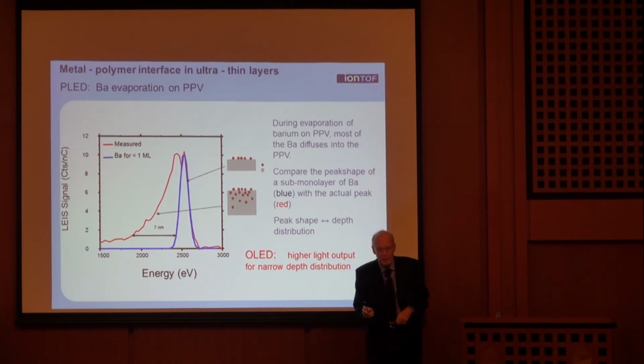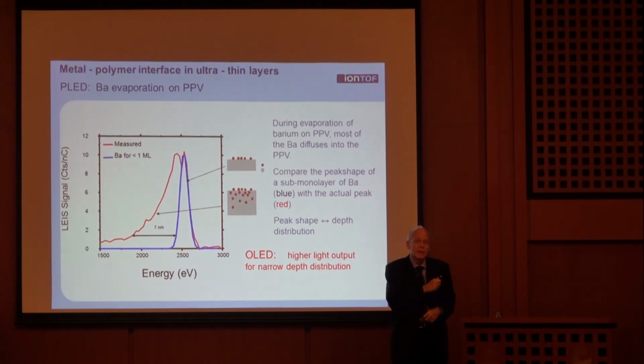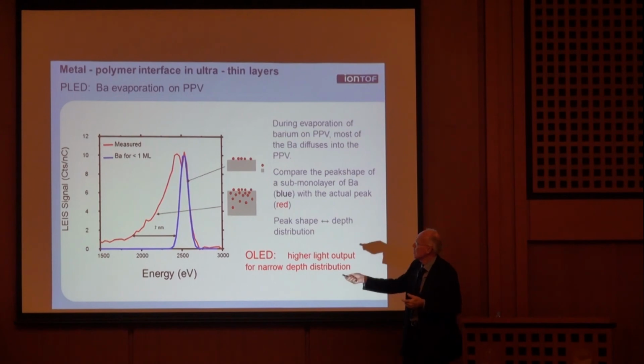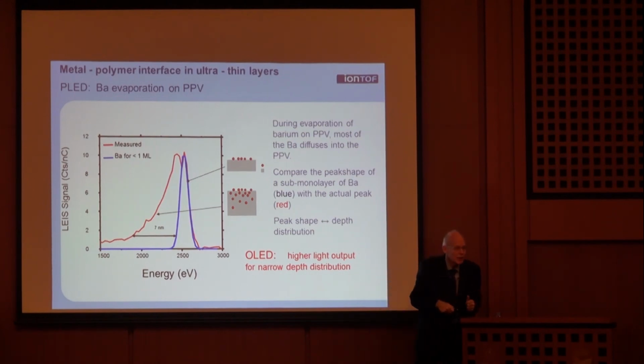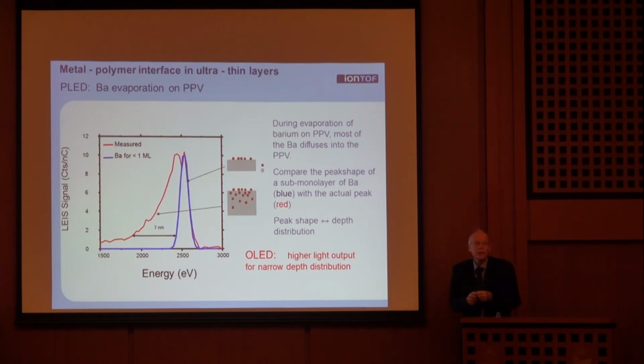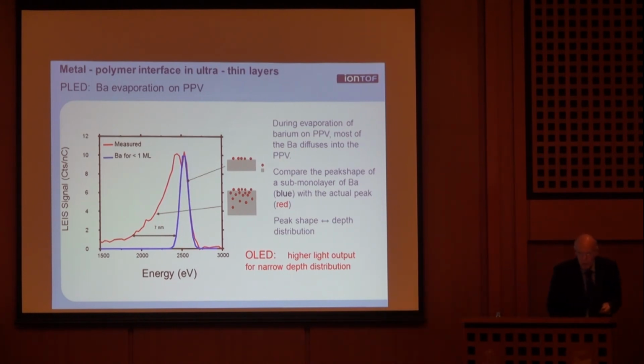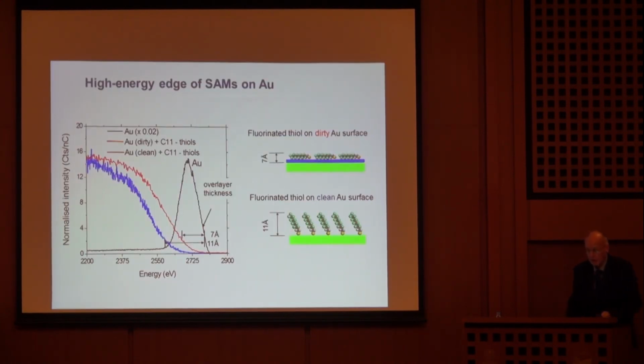Now, the amount of light that you get out of an OLED depends on the sharpness of that interface. So once you can measure this, we use that in situ to optimize our process to get sharper interfaces. And in that way, we could gain about a factor of 3 higher light output by having a very sharp interface. So there's a lot of work, in fact, also in polymers where you can use this technique. I'm close to my time.